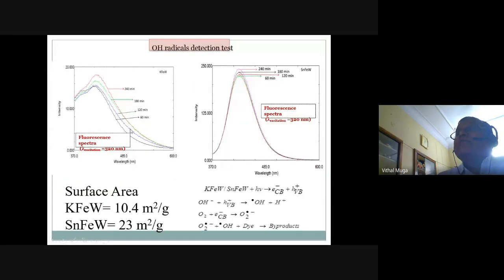Now, this is the fluorescence spectra we measured. Fluorescence spectra, or PL spectra, we call it photoluminescence spectra, indicates that the hole and electron recombination leads to some fluorescence signal. Now, this fluorescence signal is found to be actually minimum for SNFEW. Higher the value, the lower will be the rate of decomposition. Now you also see that the surface area of the ion substituted material increased more than 2 times.